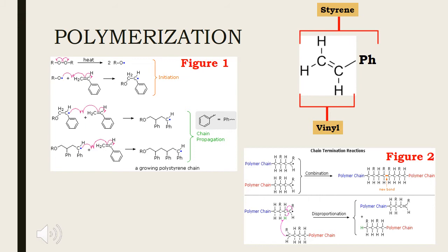Since carbon radicals are stabilized by substituents of many kinds, that's why most addition polymerizations prefer head-to-tail regioselectivity. Since radicals can tolerate many functional groups and solvents, including water, radical polymerizations are widely used in the chemical industry.